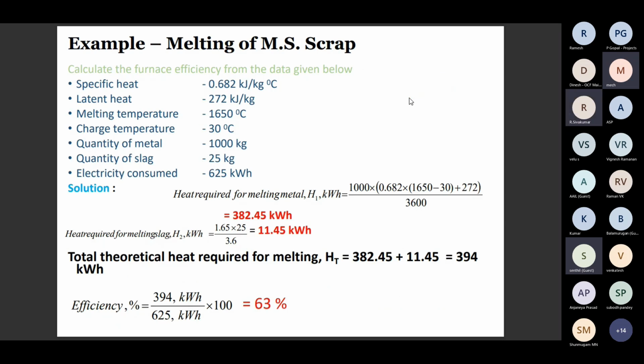Here is one simple example. We are melting MS scrap with a specific heat of 0.682 kilojoules per kg. The latent heat of the MS scrap is 272 kilojoules per kg, which is a constant value only, and the melting temperature is 1650 degrees. Charging temperature: the metal is charged at 30 degrees, that is the ambient temperature. Quantity of metal melted is 1 ton, that is 1000 kg, and out of this 1000 kg, the quantity of slag is 25 kg.